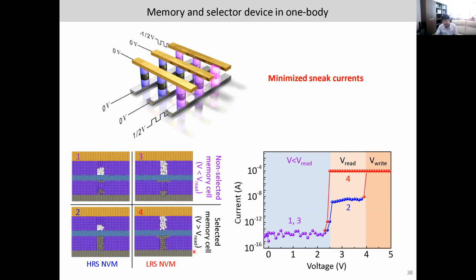For the selected memory, we have high voltage application. With high voltage, we keep this silver filament. And then this voltage cannot change the boron vacancy connection. To change it, we have to apply a higher voltage. We call that the writing voltage. And for the non-selected device, we have half voltage application, so we have broken silver. So even though these states are not broken, this is non-volatile memory. Here I used thick hBN, as I mentioned, so we have selector behavior. This is quite non-linear behavior.